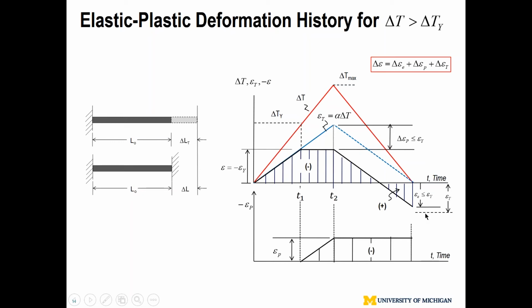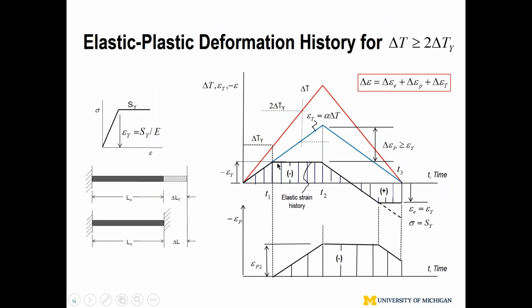Okay, fully restrained. So I expand that example a little further. If I continue to increase temperature now beyond delta Ty, what happens is, because of fully restrained, some of you may not follow with me, but at least you can work on that later if you're interested, the total strain has to be preserved. So in that case, the total thermal strain, once it reached epsilon Y or yield strength of material, all this shaded color multiplied by Young's modulus becomes stress. So this difference, blue minus this horizontal black, I get a plastic strain increasing.